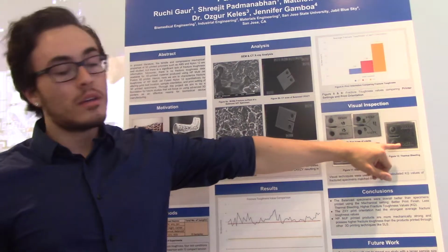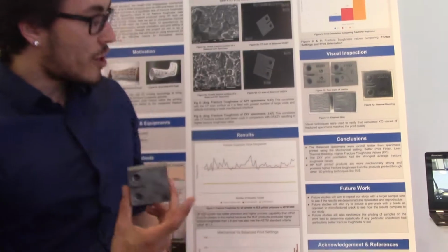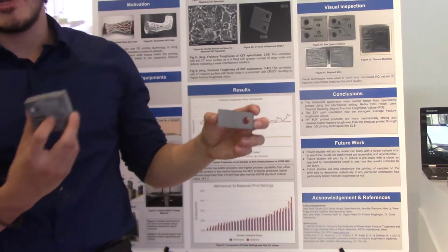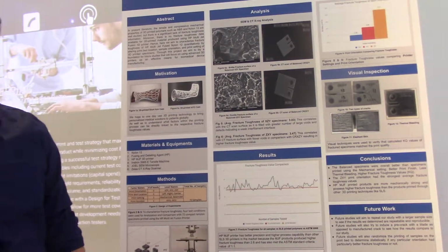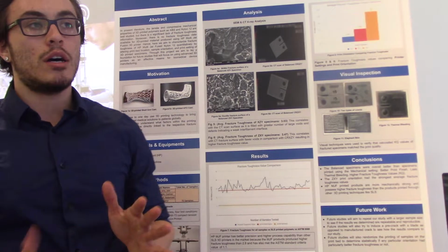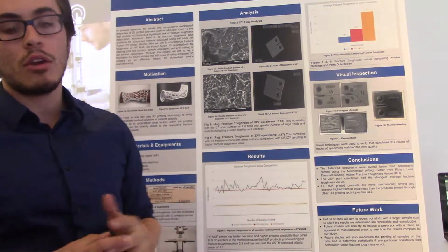Also thermal bleeding. The darker the piece is in comparison, something like this is very, very light. Darker means more heat was absorbed into the part during the printing process, which is not good. It kind of means that it got burnt. We're going to look at that and see whether we can match the amount of thermal bleeding to the calculated KQ values.